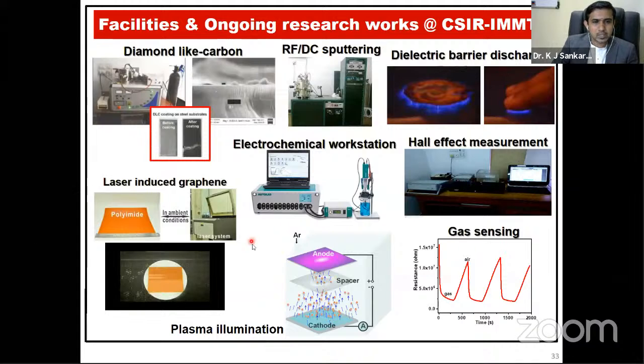And this is the recent system to achieve laser induced graphene on a polymer substrate. So this is the graphene that can be achieved on the polyimide substrate that we can use for some flexible devices, and this is the plasma illumination device which was fabricated recently by my PhD student, and the gas sensing system with my colleague. There we can sense many gases, especially hazardous gases, to fabricate a gas sensing device.